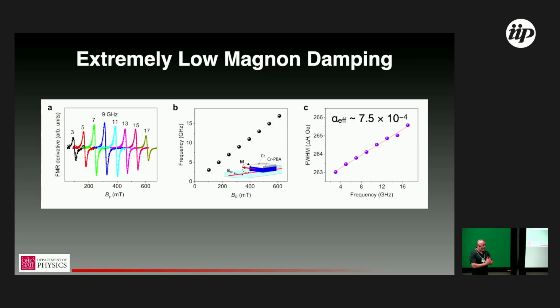So in some sense, the physics has been there for a long time, but practically, the challenge is in the magnetic materials. A more realistic value for alpha for metallic magnets is 10 to the minus 2, something like that. Getting into 10 to the minus 3 requires an enormous amount of work, and there's only one material historically that got into the 10 to the minus 5s. So using this complicated crystal structure, with a molecular basis, and getting this low damping is remarkable. You can count on one hand the number of materials that can do this.